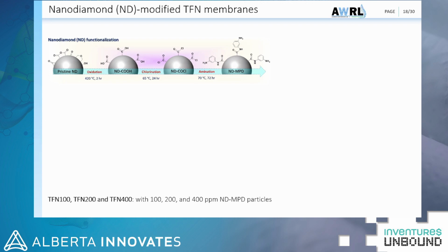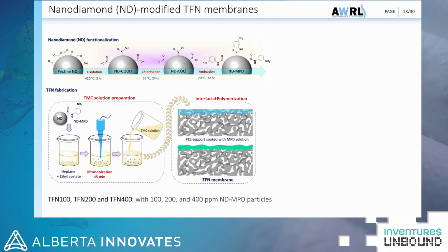So why are we doing that? Again, I recall that MPD is one of those monomers that reacts with TMC to form the reverse osmosis membrane. So we believe that if we have those monomers on the surface of the nanoparticles, they can contribute to the interfacial polymerization reaction, and they will have good compatibility with the polymer matrix. And these functionalized nanodiamonds were then added to the organic solution. Then the TMC solution was added to this mixture, and the mixture was used in the interfacial polymerization reaction.